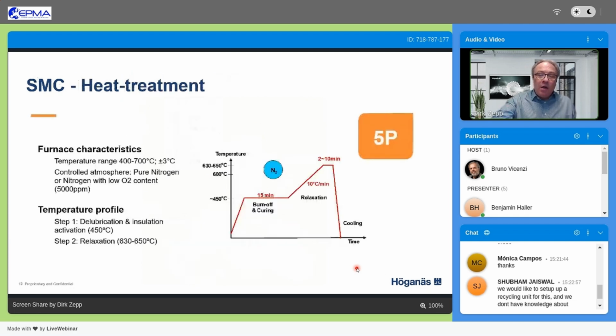Just one short example, especially for those of you who are not, let's say, involved with SMC heat treatment on a daily level. As I said earlier, we have a production-ready material, so there are certain specific heat curves for the furnaces. At the first step, after heating up to around 450 degrees, we have a certain stable time frame where the burn-off of the lubrication has to take place.